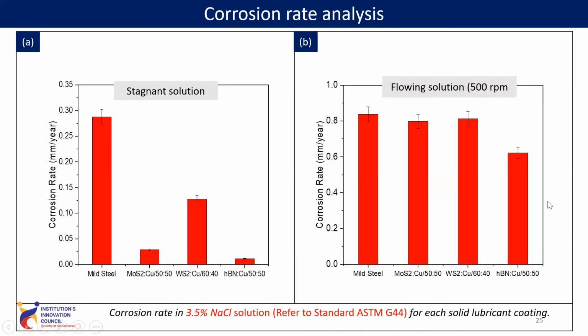We obtained stagnant and flowing water solution results for the different coatings. The minimum corrosion rate is observed for the HBN-copper coating, at stagnant and at flowing, at both conditions. So all these coatings showed less corrosion as compared to mild steel.